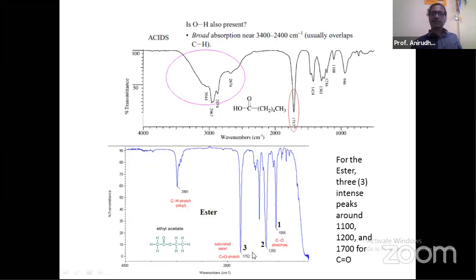So an ester is characterized by a C double bonded O formation. If there is a C double bonded O fragment in your surface film, then this spectrum from your IR will show a peak which is close to 1710 to 1725 wavenumber, in units of centimeter raised to -1. And if it is an ester, to confirm it, you will see two more peaks, one corresponding to 1056 centimeter inverse and the other corresponding to 1250 centimeter inverse. So you can use IR also to get useful information related to the chemical nature of your surface in terms of their functional groups.